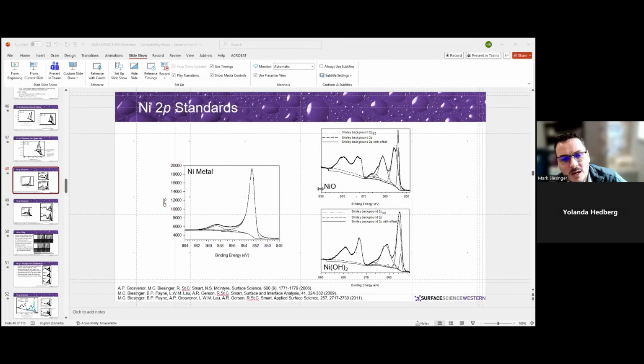If the defective oxide peak is too wide, how do you know what figure to constrain the full width half max to? Good question. It will depend a little bit on your spectrometer, but for the most part, a maximum of about 2 eV is kind of where that limit is. And we base that on analysis. We've done a lot of different samples. I do show on the website all those other peaks that are present for a lot of the transition metals, and they're all in that 1.5 to 2 eV maximum width, as opposed to the lattice oxide, which is generally thinner, 0.7 to 1.2, 1.3 eV, something like that.